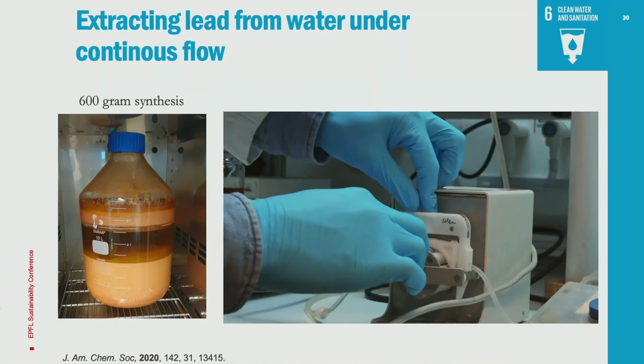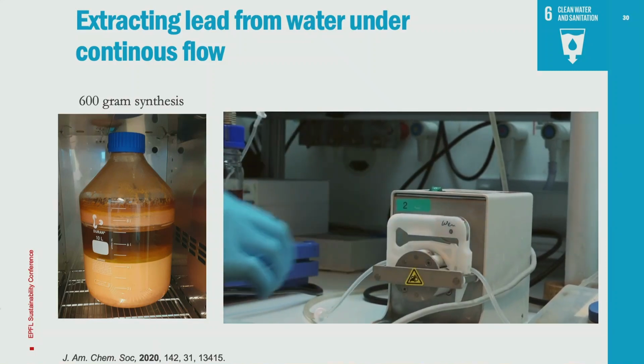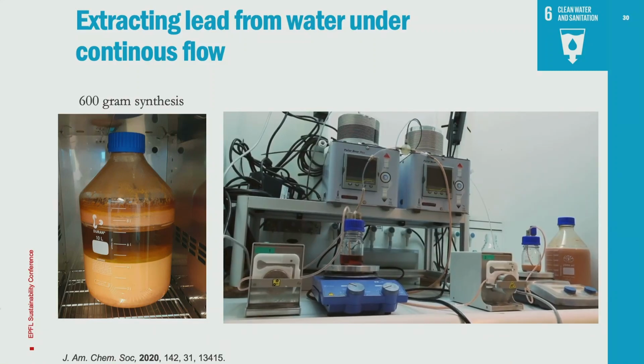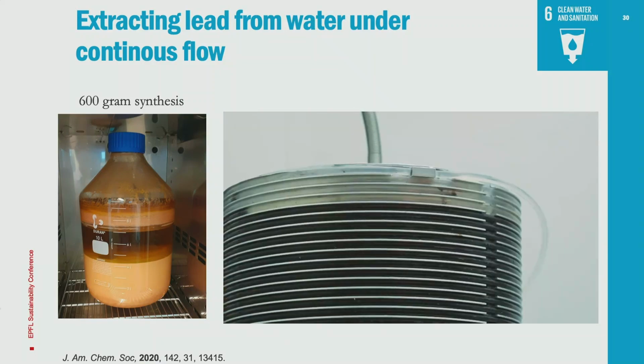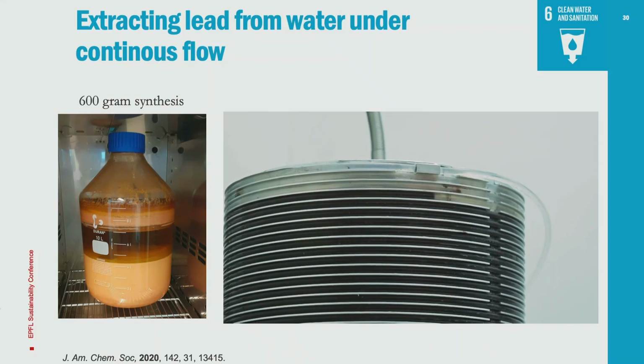Here you can see a flow-through process that we're using for our polymerization. So here's our MOF over here. Here's our monomer here. They literally flow together on this column, which is heated. And then we pump the MOF polymer composite back out on the back end. So this is the formation.